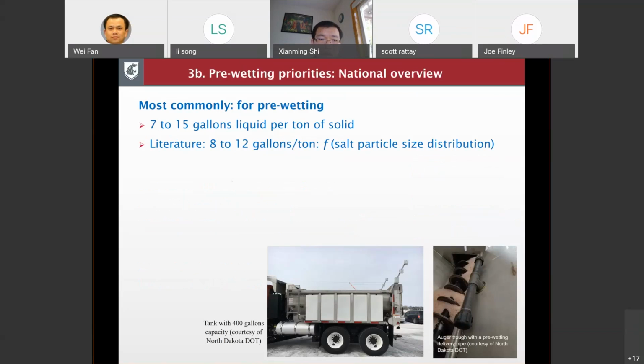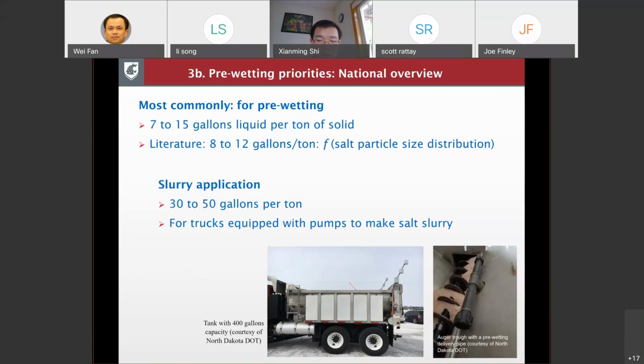Now, nationally, we're talking about a typical application rate of 7 to 15 gallons per ton of solid salt. And according to literature, that range is a little bit narrower, 8 to 12. Usually it's a function of how large your salt particle size is. And then there's also a very interesting deviation from the typical pre-wetting, which is a slurry. Basically, you intend to greatly increase the pre-wet rate so that it works faster, but that requires your truck to have the pumps to make the salt slurry. So sometimes the equipment is limited and you cannot go up as high as 30 to 50 gallons per ton.